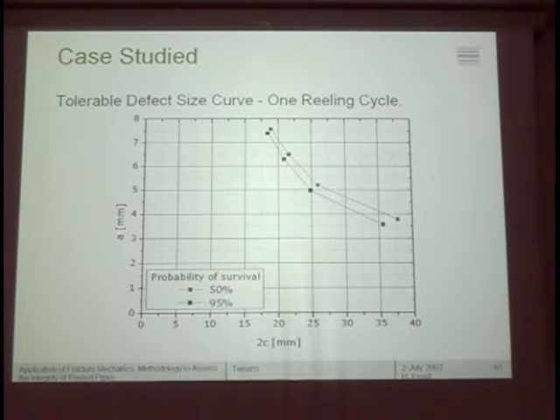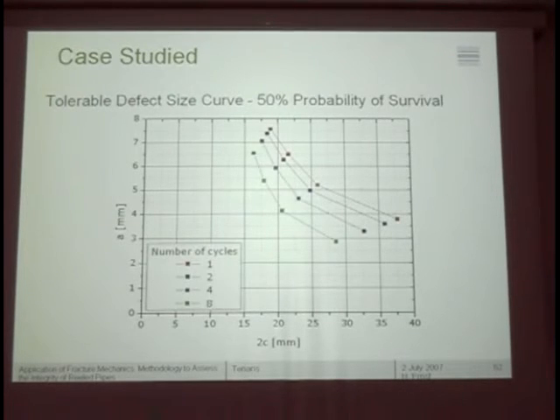This is the result that we come up with. If we want to see how the number of reeling cycles changes things, remember a reeling cycle is composed of 2 deformation cycles, so for number of reeling cycles 1 here, again, it is A versus 2C, 1 reeling cycle. If you now put 2 reeling cycles, this of course is 50%, I should have said this, 50% probability of survival. You come up with this other curve for 4, and this other curve for 8. Of course, the more cycles you put in, the closer you get to the origin, obviously.